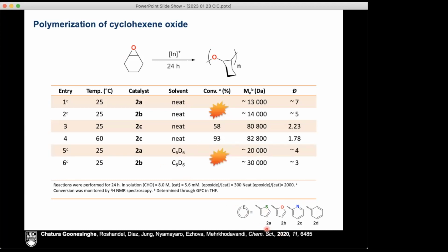Same thing happens. Sulfur and oxygen analogs here, highly reactive. The cyclohexene oxide system with a pyridine donor is very controlled, a relaxed system that seems to eventually polymerize, takes its time. So this just shows you something about the catalyst.